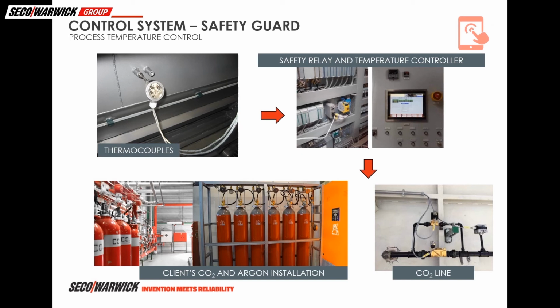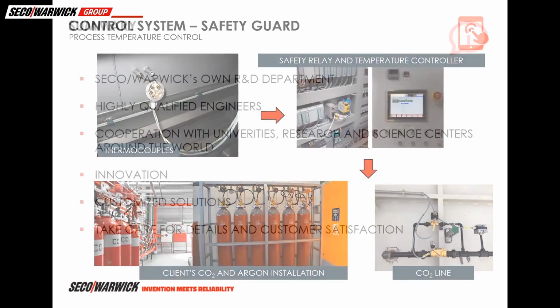The controller switching value is sent from the PLC after scanning the recipe of the current process, which is the set point of the heating segment with carbon dioxide. Exceeding the set point by 6 degrees turns off the furnace heating. When the temperature in the furnace increases further, to set point plus 15 degrees, despite the turned off heating, the argon flow is activated, while carbon dioxide flow is cut off.